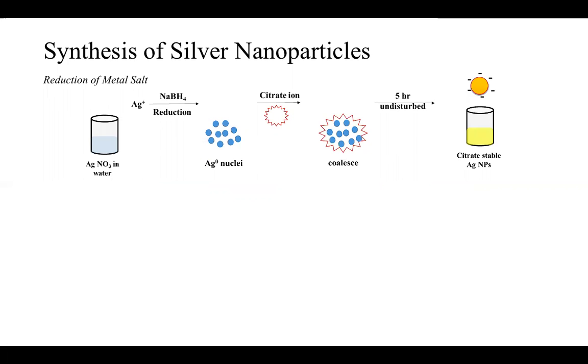So one of the first ones we looked at was the synthesis of silver nanoparticles. And this was a wet chemical synthesis method where we just used silver nitrate and water. And we were able to reduce it with sodium borohydride, a strong reducing agent, and cap it with a citrate ion. And what happened is, as this set over time, the charge on that silver became silver 0, and we were able to produce silver nanoparticles that end up reflecting a qualitative property of a yellow color that kind of indicated that we had produced silver nanoparticles.